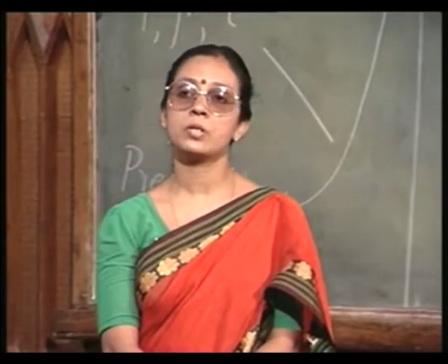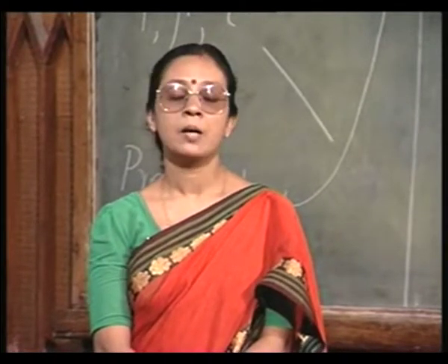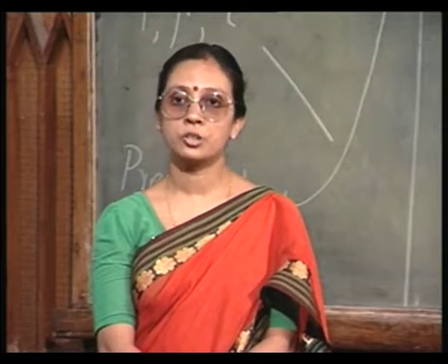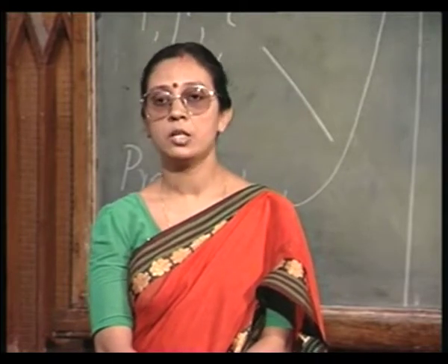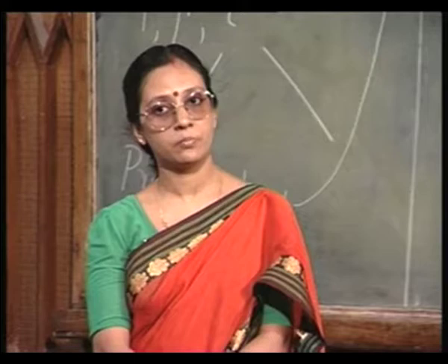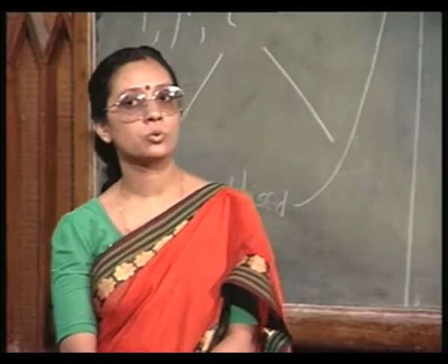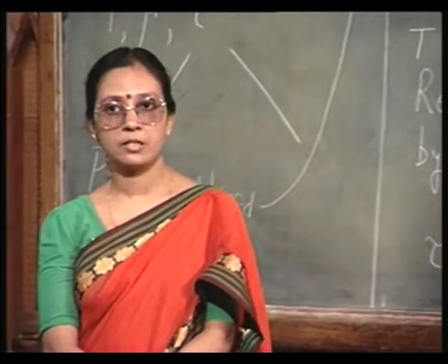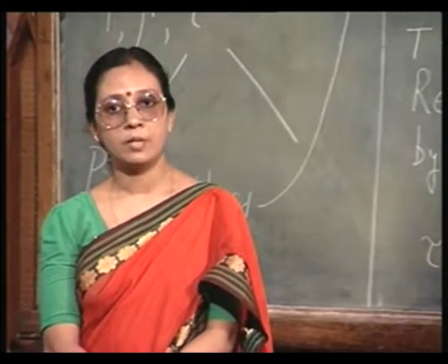But the lifetime recovery is still not there, lifetime is still very low. If you really want to get the full lifetime back, you have to go to high temperature, about 1000 degree centigrade, that will give you full lifetime recovery.